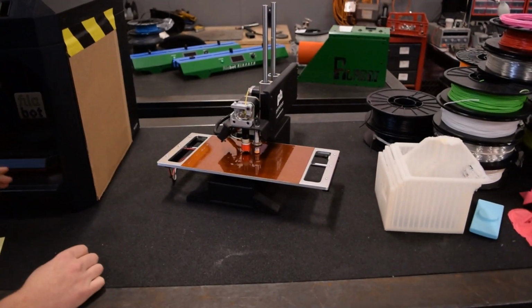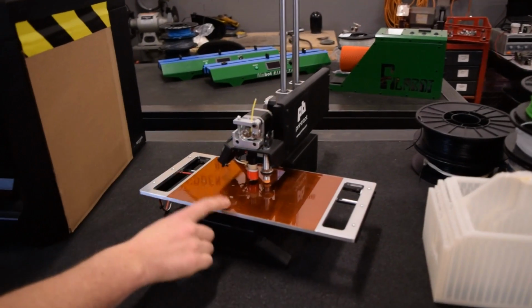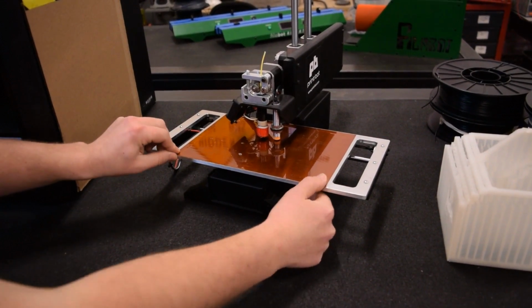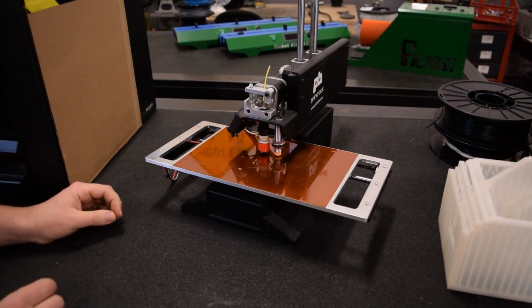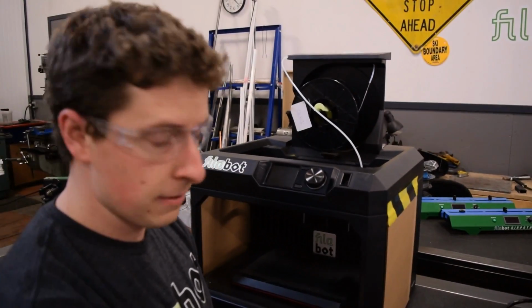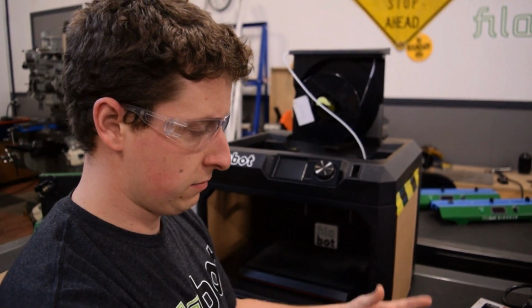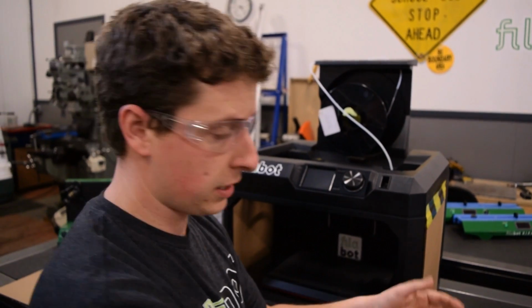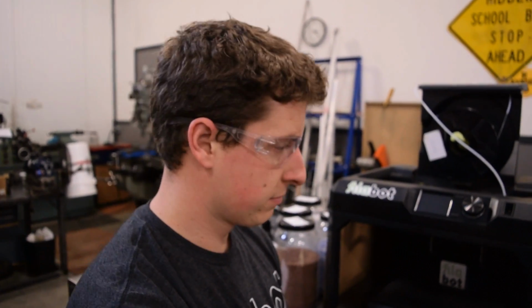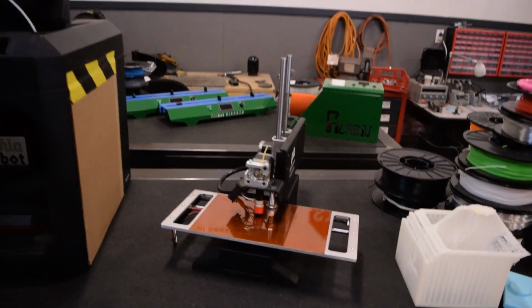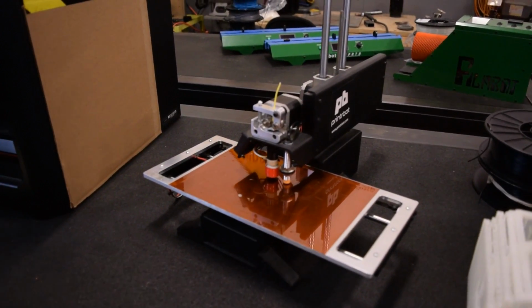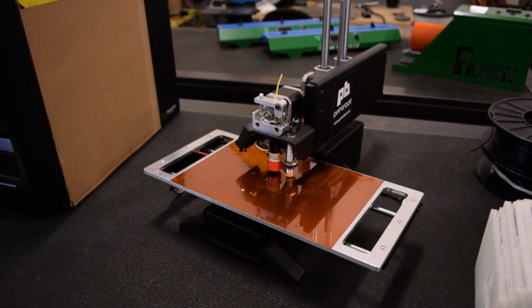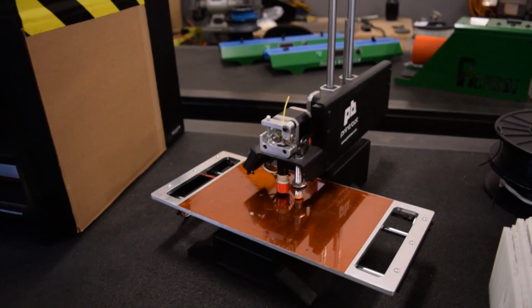Big consideration there. And then the next thing is, you can see how there are two different materials on this printer bed. We have this tape, which is called Kapton tape. It's a tape that's actually used in electronics to hold down wires inside of cases and TVs. It's a high temperature tape. Yeah. What you do, Kevin, is you use the Kapton tape with a very thin layer of Elmer's glue stick, right? Yep, for ABS specifically. Would you use that for PLA? I do not. I use the plain, because another property of PLA that isn't really on the data sheet, but that's very helpful, is that when it's melted, it has a very high stickiness? Well, the melt flow is high. Okay.